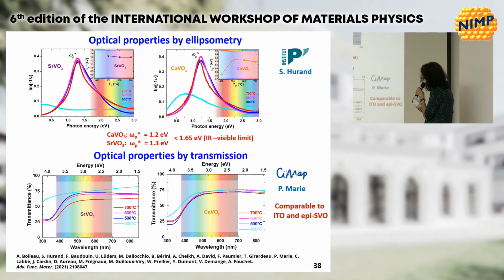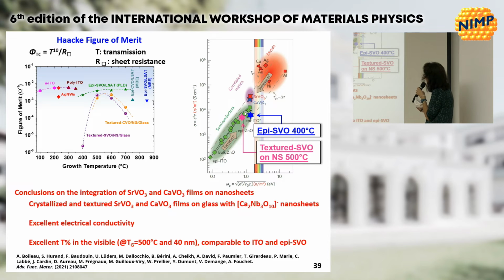By ellipsometry, the plasma frequency was also measured, and you can see that it is below the visible range. This is what we wanted, because the threshold is about 1.6 electron volts. And finally, the optical property by transmission. The transmittance was also measured, and as you can see, it is fully transparent and comparable to what we have with indium tin oxide. If we put the results in a figure of merit, we can see that our results are close to the other transparent conductive oxides, and this is really a good result. And if we look again at this diagram, we see we are here, and it's not so bad.